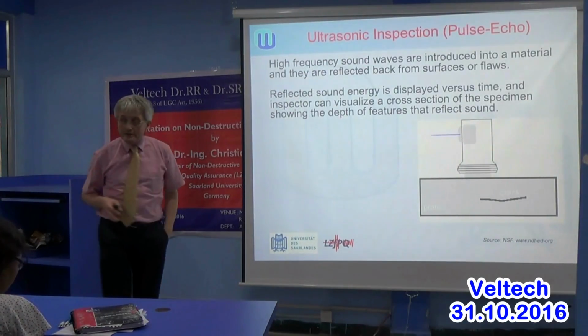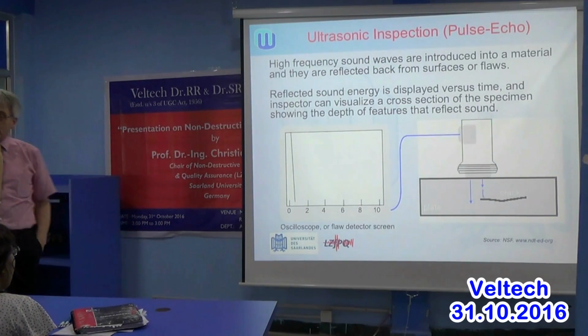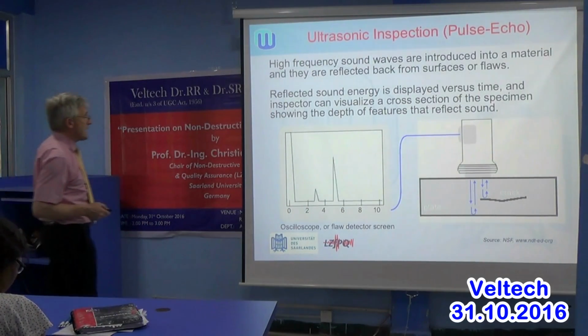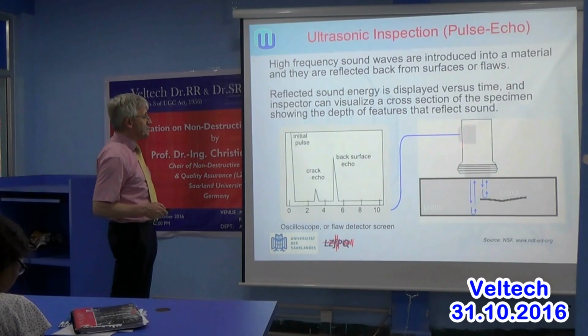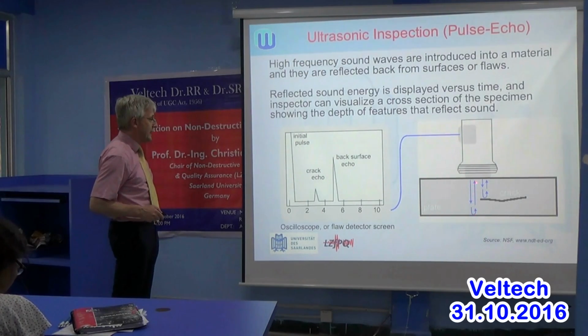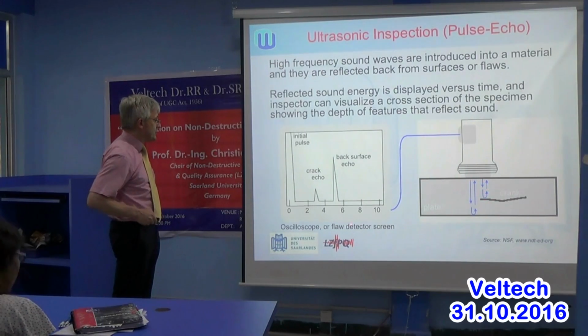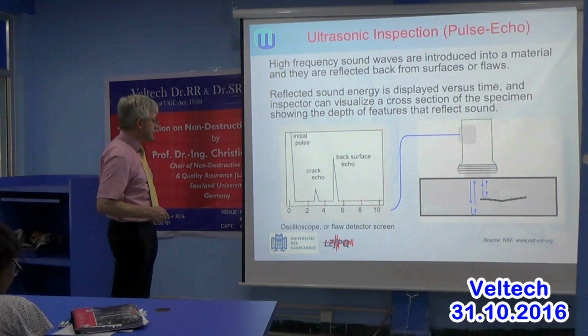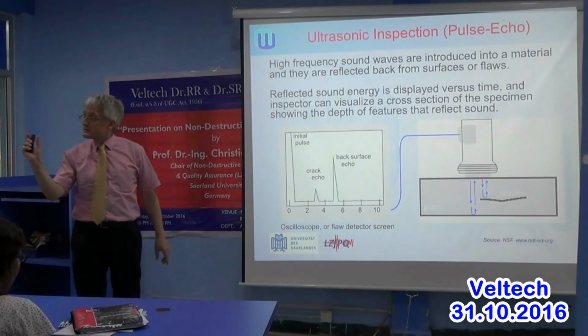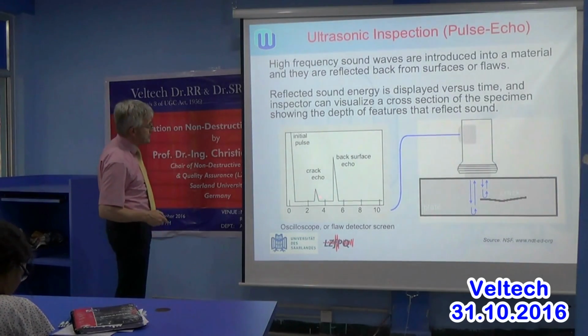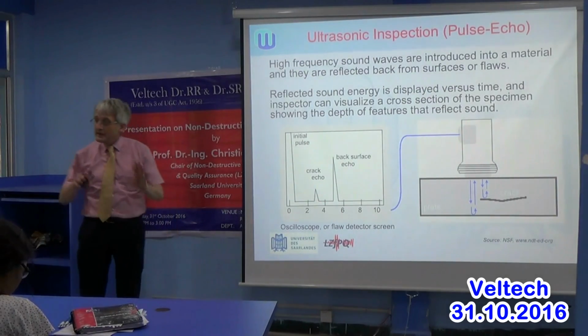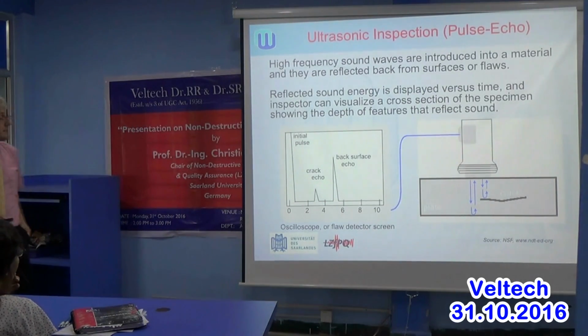Then we have ultrasonic, a technique which is, after visual, possibly the most used. What we have here is that we send in an acoustic impulse, and the acoustic wave goes through and is reflected, interferes, and goes back again. If we have a flaw, then it's reflected a little earlier, and we take a time signal here. So this is the initial pulse. This is what we call the back surface echo coming from here. So we can do, for example, thickness measurement with it. And if we have a flaw in between, we'll get signals in between. So we'll see if something is not perfect inside that material.